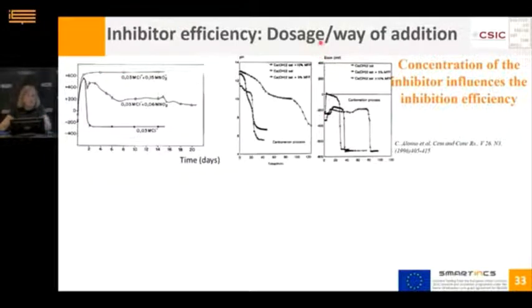When we have the risk of carbonation, there is a decrease due to the decrease of the pH. You can observe that there is a difference depending on the concentration of the monofluorophosphate. This is because the phosphates, when they interact with the pore media, form calcium phosphate that is very insoluble, but the pH increases. So this creates a retard in the pH drop during carbonation, but at the same time there is a retard in the corrosion initiation with the presence of the inhibitor in increasing amount.